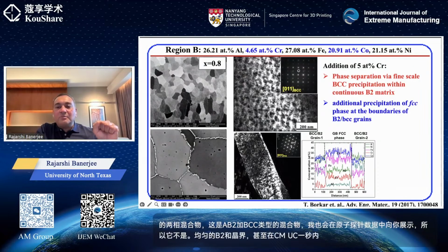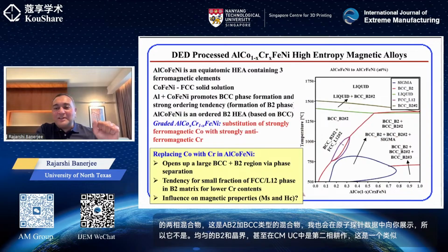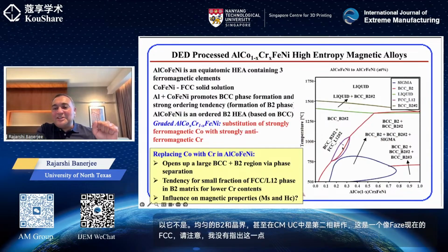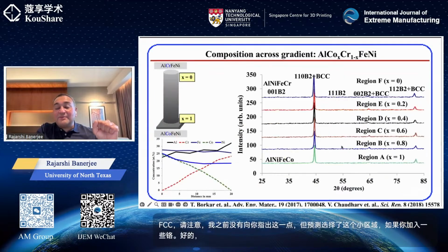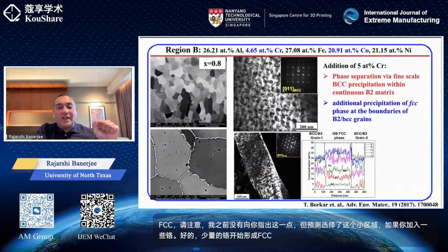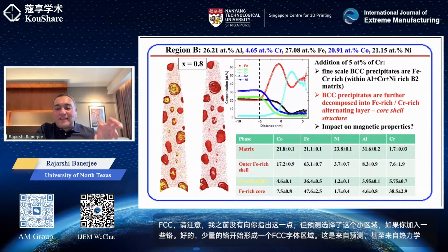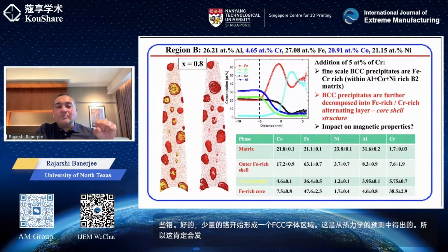Now, mind you, I did not point this out to you earlier, but the prediction shows this little region here: if you add a small amount of chromium, you start forming an FCC type phase field. This was from the prediction, even from thermodynamics or Thermo-Calc. So this is definitely happening. But this actual microstructure at a higher resolution in the atom probe is very interesting.